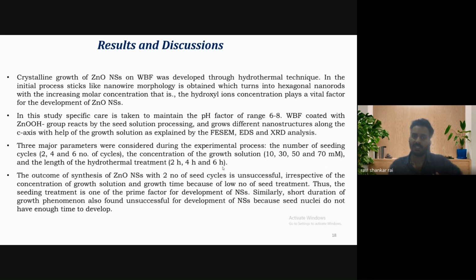Three major parameters were considered during the experiment: the number of seeding cycles, that is 2, 4, 6; the concentration of growth solution, 10, 30, 50, 70; and the length of the hydrothermal treatment, 2, 4, 6. At a low number of seeding cycles, there was very low initiation of the seeded particles. That is why the samples did not perform well. And if the length of the hydrothermal treatment is short, it does not have enough time to grow properly. So we must maintain the number of seeding cycles along with the duration of the growth treatment.